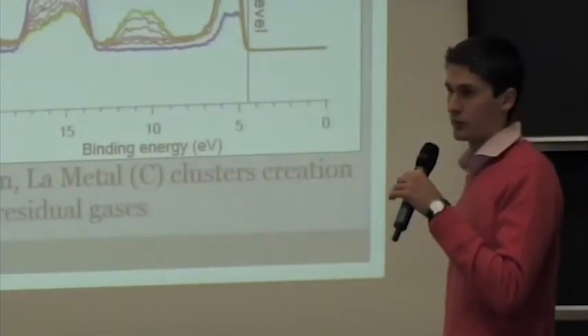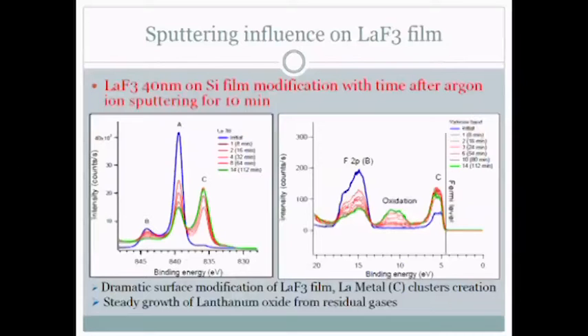Also, sputtering was performed, and it gave quite unexpected results: after sputtering, all the surface is slightly distorted, and it's easy for the beam to deplete fluorine from the surface. And as you could see here, after 8 minutes, we received a completely different picture of the surface.